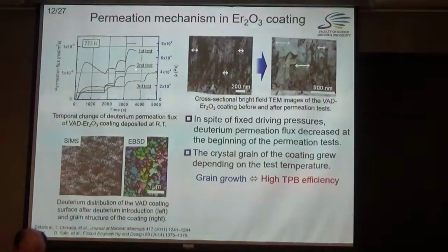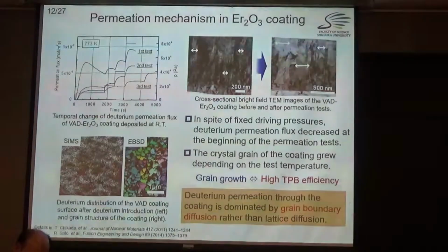With the TEM observation, this is a cross-sectional bright field TEM image. So the columnar structure is bigger after the permeation measurements, then the permeation decreases. So that's an important change. Another thing is that this is a surface deuterium distribution with SIMS. So then the grain structure is like this. So it's really close to a closed network structure like this. So that means hydrogen or deuterium can permeate fast at the grain boundary. So this is called grain boundary diffusion. So the deuterium can permeate fast not in the crystal, but in the grain boundary. So the grain boundary is the main path for deuterium migration.